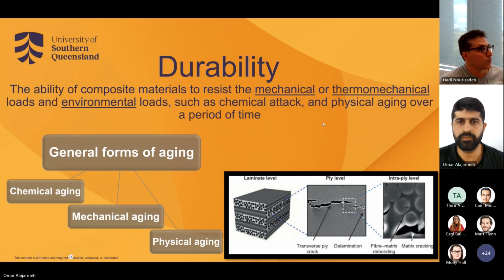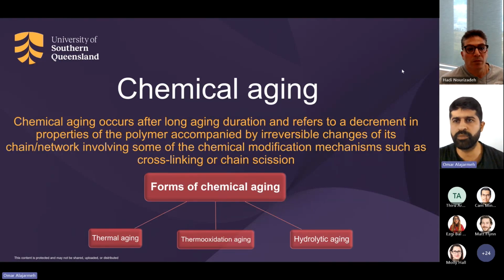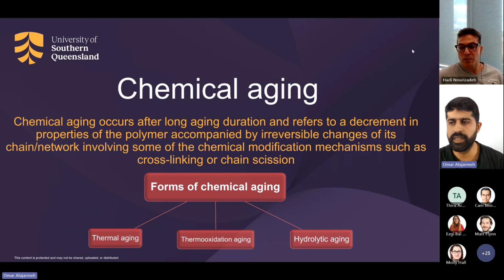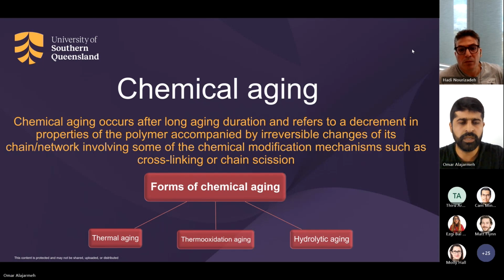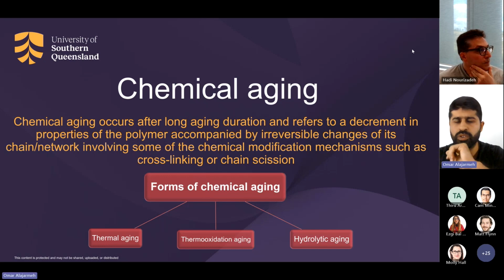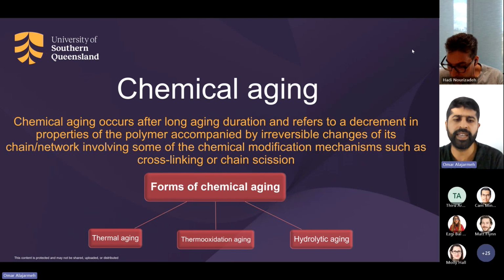Starting from the first factor, which is a critical factor of aging, we are talking about chemical aging. Chemical aging occurs after long aging duration and causes a decrement in properties of the polymer and changes in the chain and cross-linking of the polymer. That changes the whole properties of the polymer. The forms of chemical aging are thermal aging, thermo-oxidization, and hydrolytic aging, all related to chemical aging.